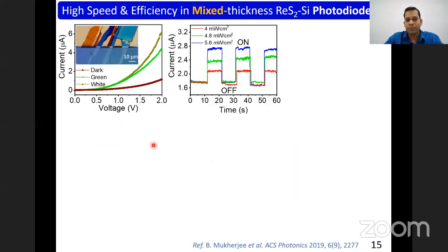So here what we observe is that if we use this rhenium disulfide with different thickness and make this type of photodiode, then under light illumination with different wavelength, we can see a manifold increment in the photocurrent. And this current with time shows that under successive on-off of the incident light, the current also follows the incident light illumination pulse. So it is strongly reproducible, and it is quite fast, and it follows the power law. So basically, if we increase the intensity, the current also increases.